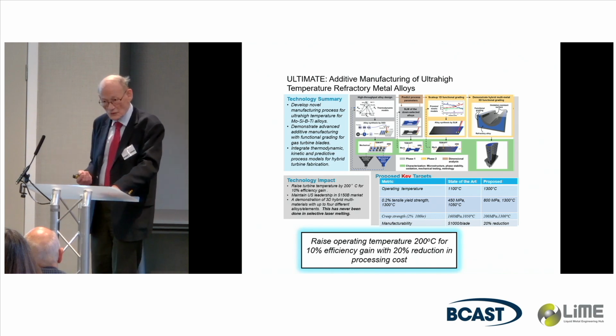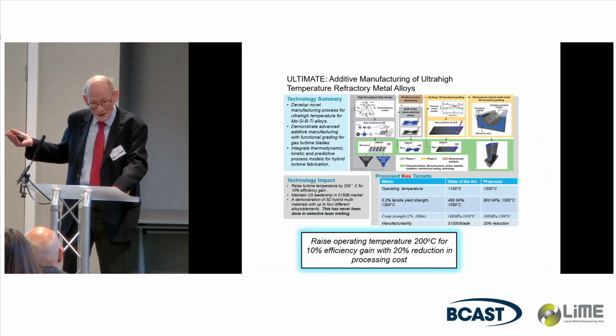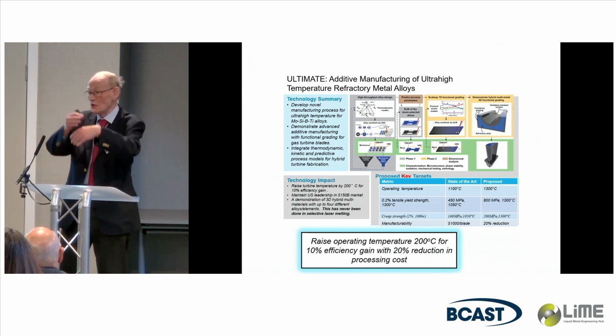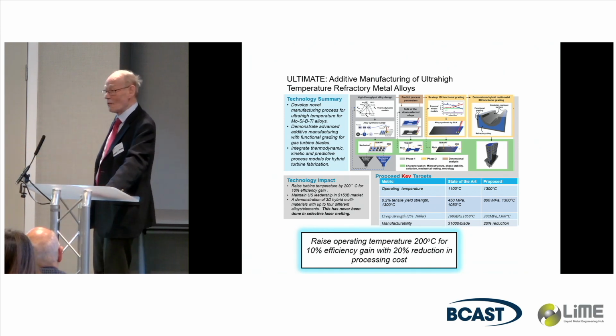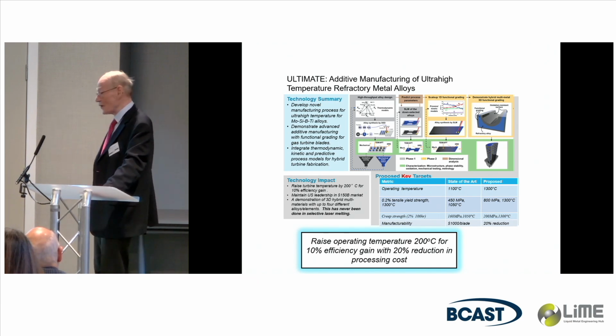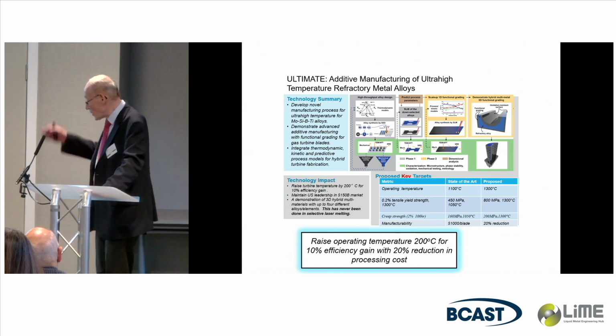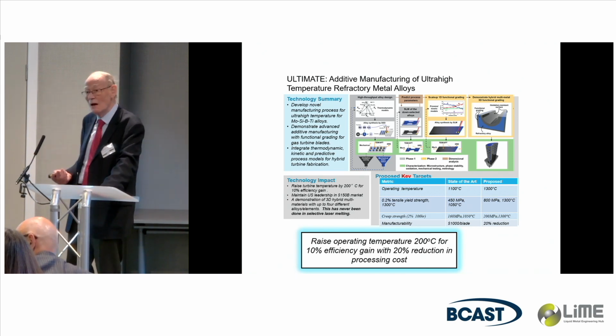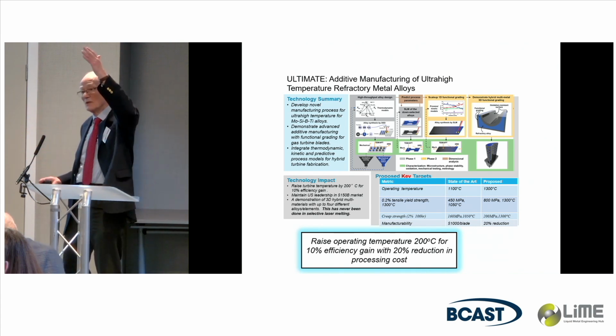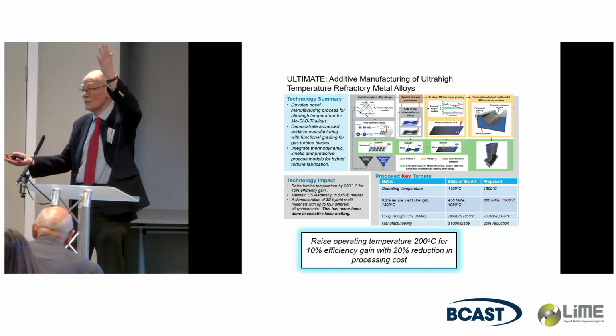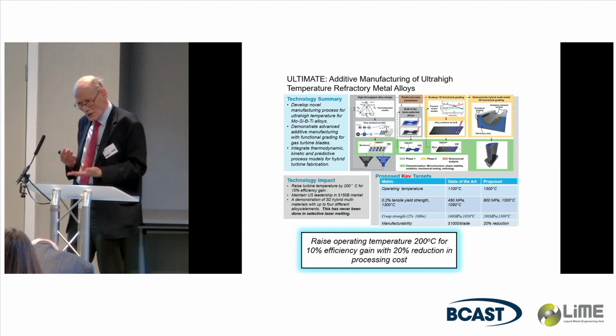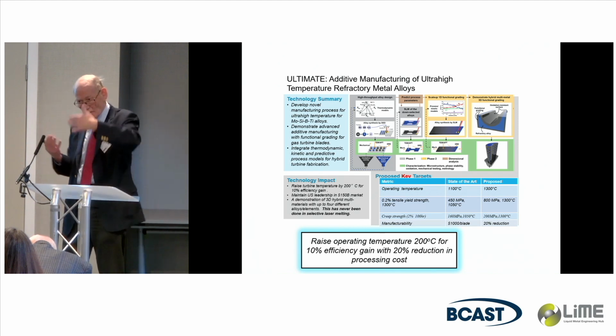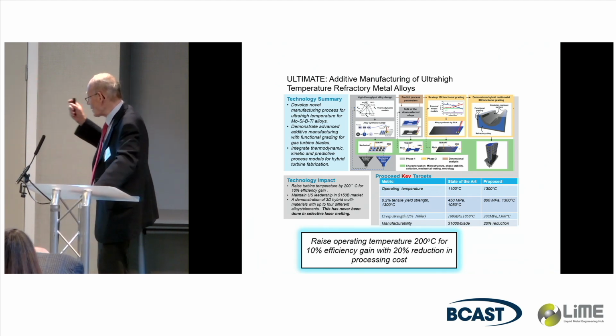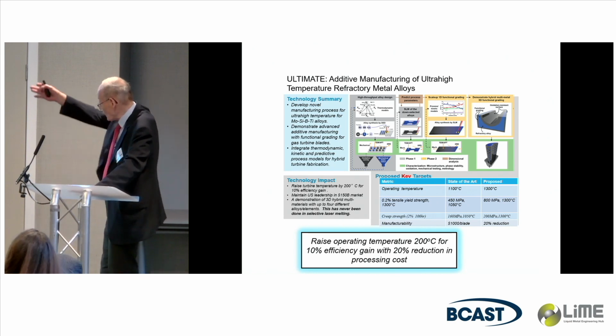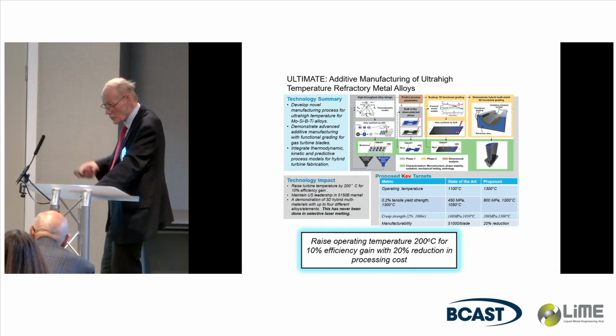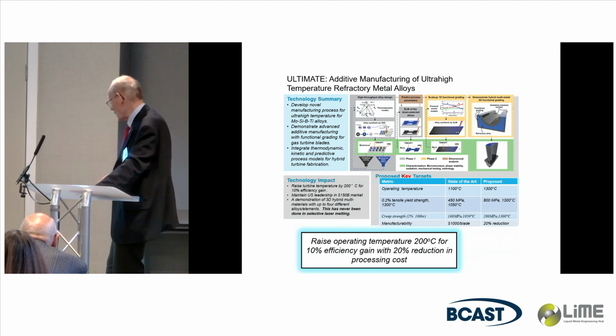But is titanium 6-4 the best alloy for additive manufacturing? I doubt it. But how do you do screening of different alloys when you have to rely on alloyed powder? It's very expensive to do a powder run. Well, you can take elemental powders and try to melt them, but if you have things with vastly different melting points, titanium and aluminum, your composition control is kind of tricky, because once you're melting one component, you're vaporizing the other. So how do you do this in a reproducible fashion? Because additive manufacturing is perfect for doing high throughput screening, if you could do it.